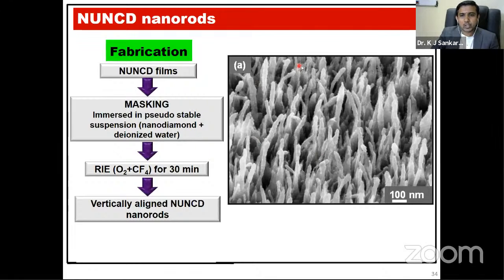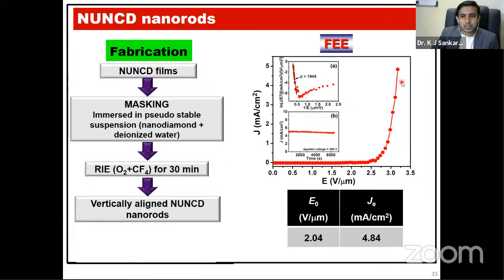If you look at the field electron emission properties of these NUNCD nanorods, they are much better than the NUNCD films, and also the beta enhancement factor, as I mentioned earlier, which represents the high aspect ratio, is very high, around 1945. Also, if you look at the lifetime, applying a voltage of 200 volts gives a very high lifetime stability of more than 6,000 seconds. So NUNCD nanorods show very good field electron emission properties. So this is one way of making NUNCD nanorods.